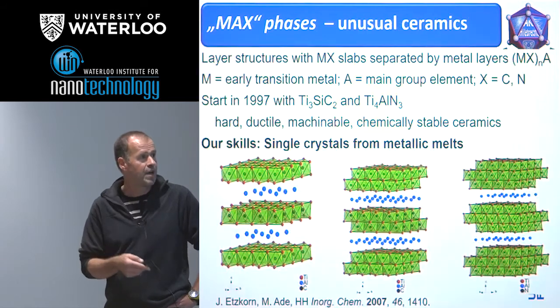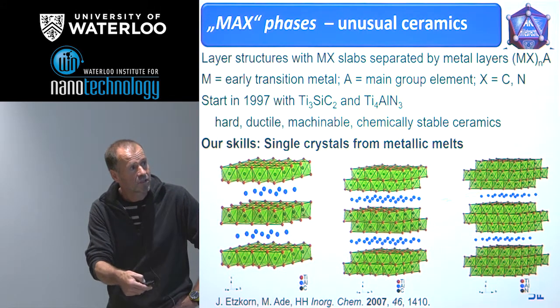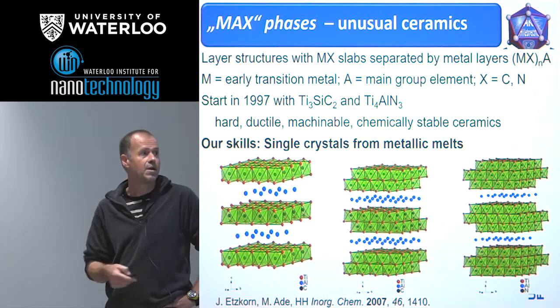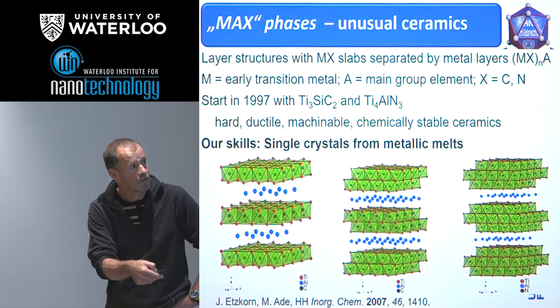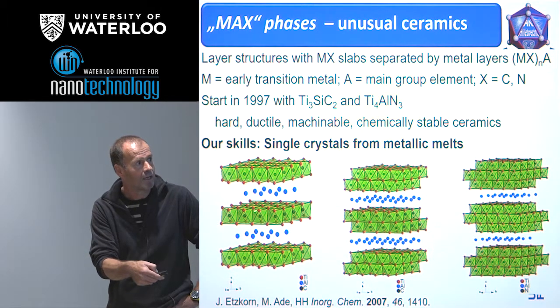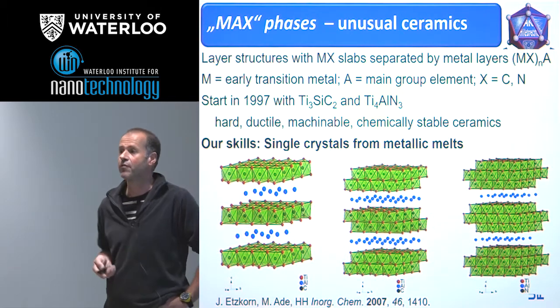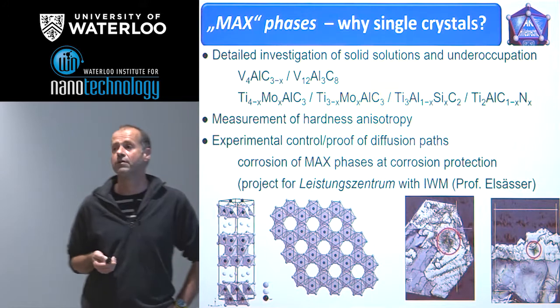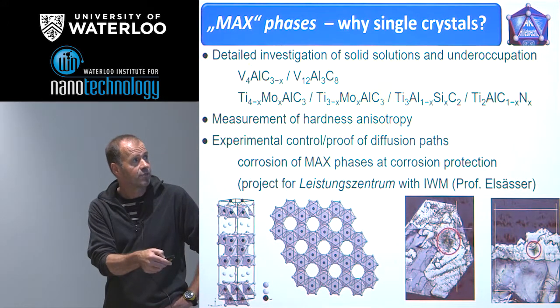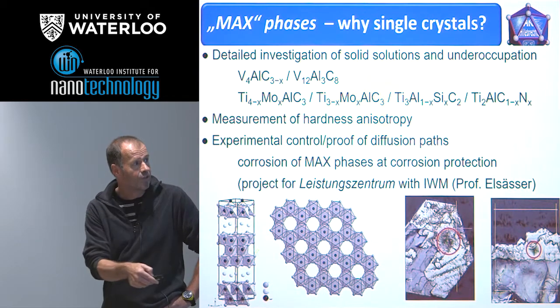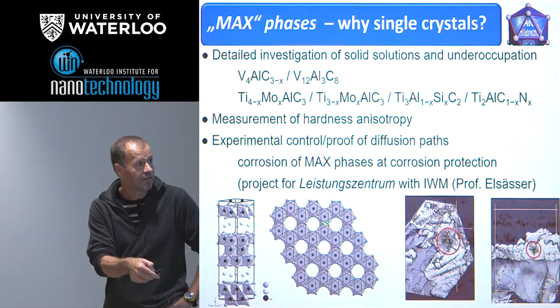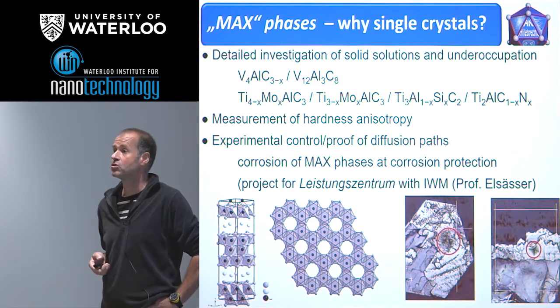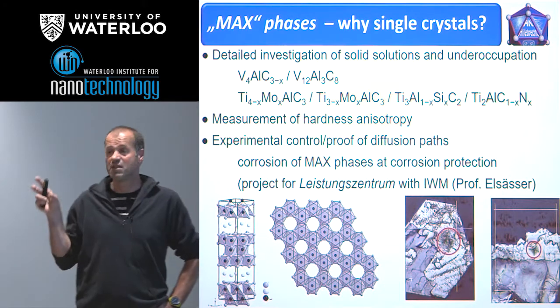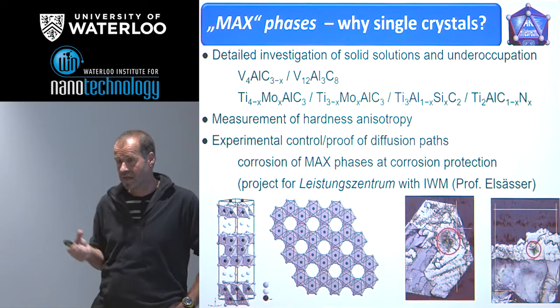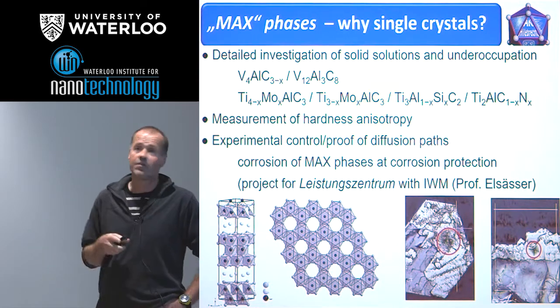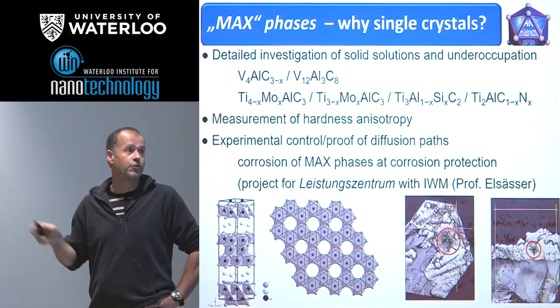And so the idea is, if we have a ternary compound which shows this close similarity to the binaries, that means the increased content of transition metal carbide, according to n, is managed by an enlargement of the thickness of the layers, then we should expect the same phenomenon. We could show several years ago for the system with vanadium, aluminum and carbon that indeed there are ordered or disordered vacant sites for the carbon positions, and that the stoichiometric composition is not stable. Very recent calculations and also measurements have shown that indeed the deficit is fundamental and necessary for the stability of these MAX phases.